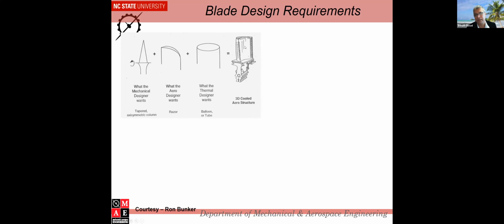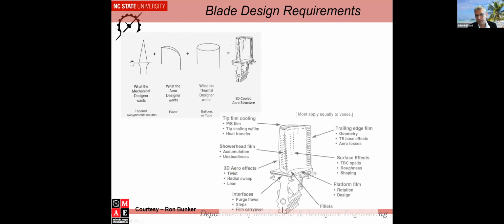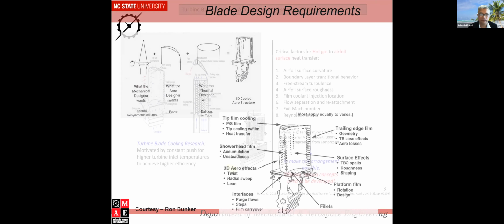Then I add all these holes as a thermal designer to let cooling air come through, and inside the blade, there are a lot of passages. Outside the hole itself, there are different kinds of effects. You have surface effects, you have trailing edge film that's coming out of the back of the blade. You have fillets, which help you connect the blade to the base. You have interfaces. That means where there is a gap, where the rotating component and the non-rotating component are mismatched. So there has to be a gap there. There will be a seal there, but the seal is not perfect. Then you have 3D aero effects, and then of course you have all kinds of holes coming out everywhere, and all these contribute to heat transfer problems.